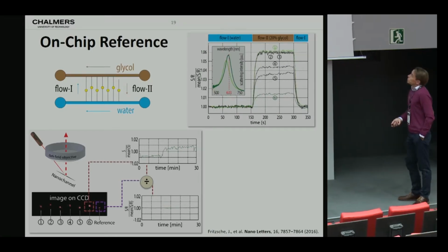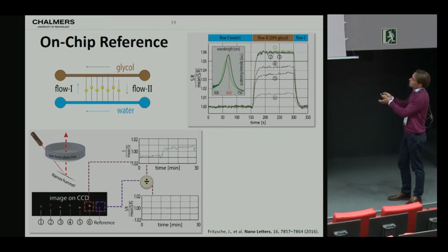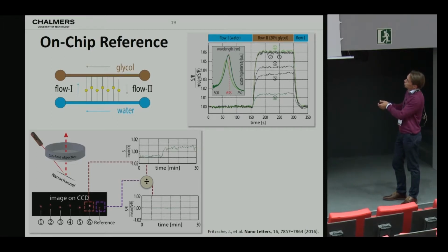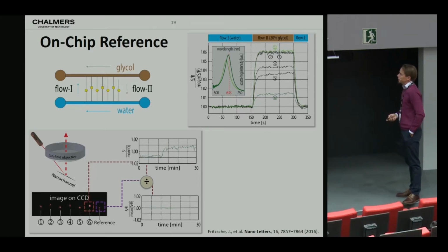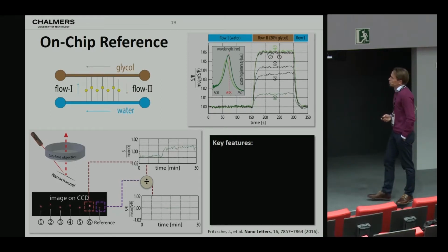You can do the first simple experiment, again exchanging the fluid and doing the refractive index sensing, where you get this very nice and smooth response, perfectly reversible, with the highest signal actually stemming from a particle that does not resonate at the laser wavelength, but where the laser wavelength coincides with the flank of the particle, as you would expect. So what are the key features of these experiments?